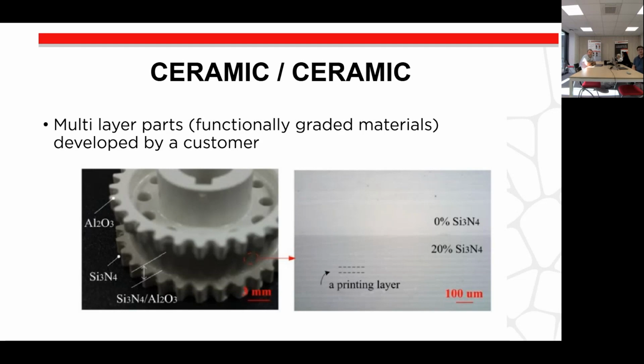The idea in here is to mix Si3N4 with alumina and to have an interface between silicon nitride and alumina in the middle. So you can see on the right-hand side, on the picture on the right, you can see the printing layers. The idea is to have 100% silicon nitride at the bottom, 100% alumina at the top, and a mixture with 20% of silicon nitride in the middle to make the transition between both materials.